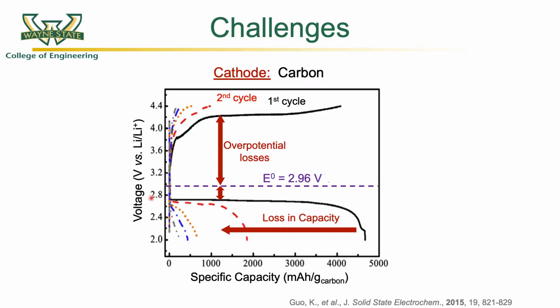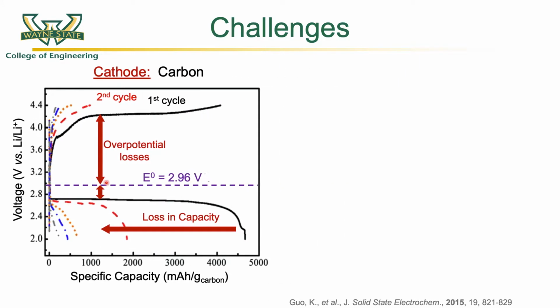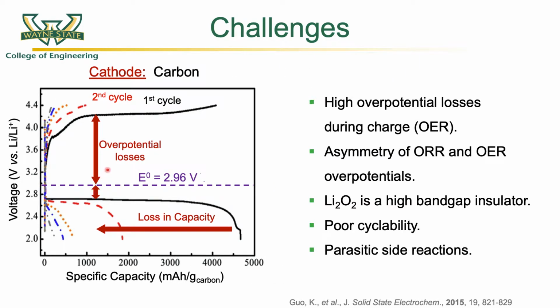What this curve represents is the potential response when a constant current is applied to the cell. Since the current is held constant and the x-axis represents the charge per unit mass, this essentially becomes a time scale. The first thing that you notice is the large asymmetry in the overpotential losses during the discharge and the charge cycle. This high overpotential loss is associated with the insulating nature of Li2O2, which is a high band gap insulator.